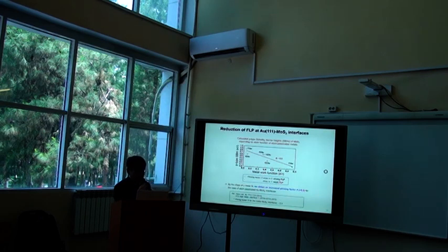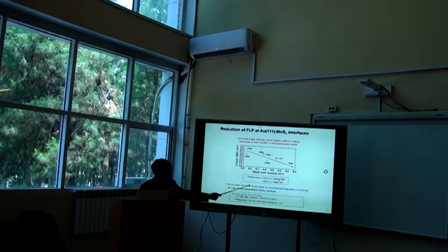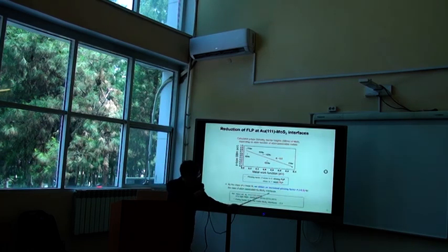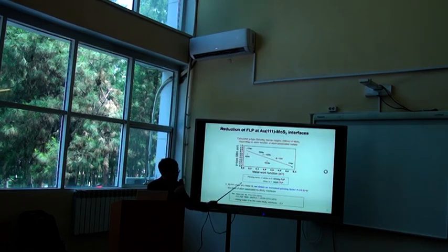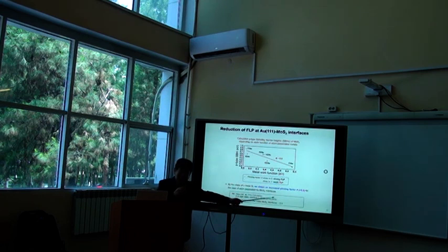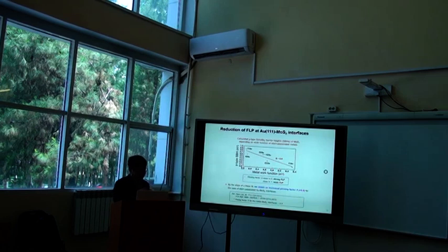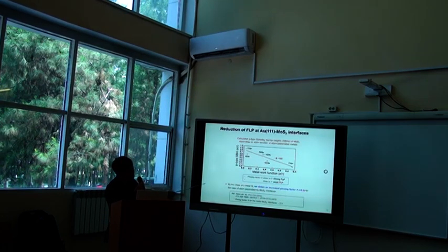Previously, using clean surfaces, another group obtained a pinning factor of 0.3 here, and we calculated the pinning factor using atomic species at the interfaces and found about 0.5, which means our result is closer to 1, implying a reduction of the strong Fermi level pinning.